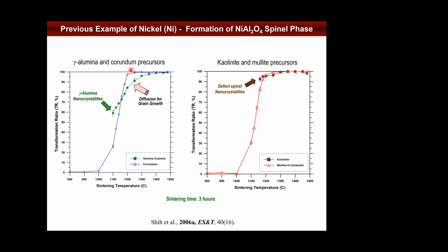The target phase is nickel alumina spinel. When it goes to a relatively high temperature range, in fact, the alpha alumina is proven to be more capable of capturing the nickel and becomes a stabilized phase, nickel aluminum spinel as well. So this tells you the mineral phase is very important.